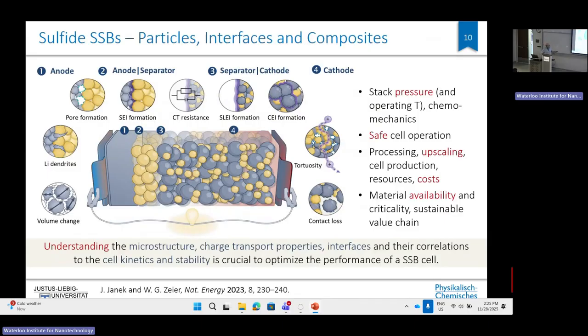This is a bit different cartoon of such a reservoir-free cell. We have a separator electrolyte that should be rather thin. I would say 10 micron. Modern separators in your smartphones are even sometimes thinner than 10 micron. You need a thick cathode. Thick because you have to store there lots of lithium. You need a high areal capacity in order to get a high energy density of your cell. And then here the lithium is being cycled.